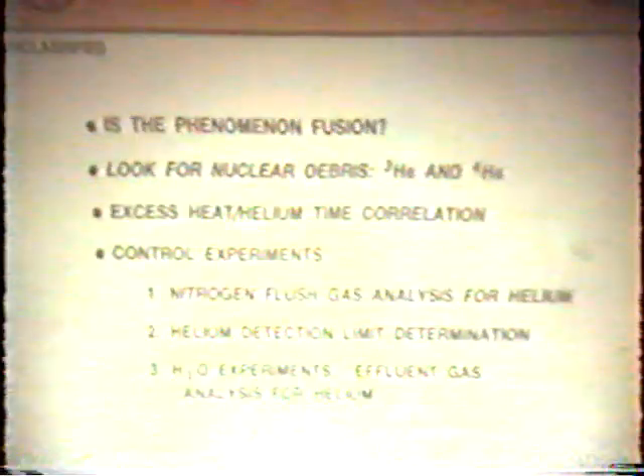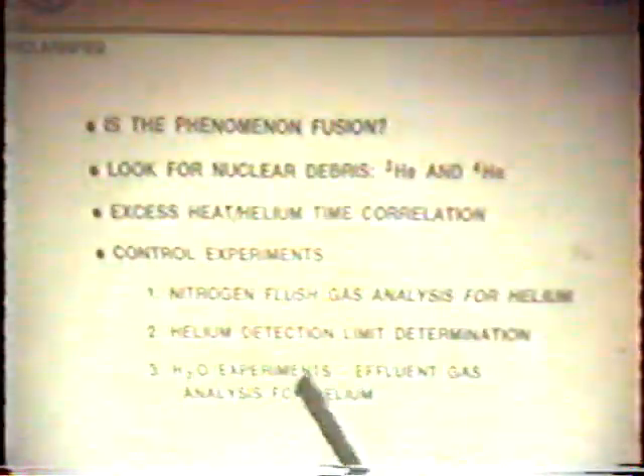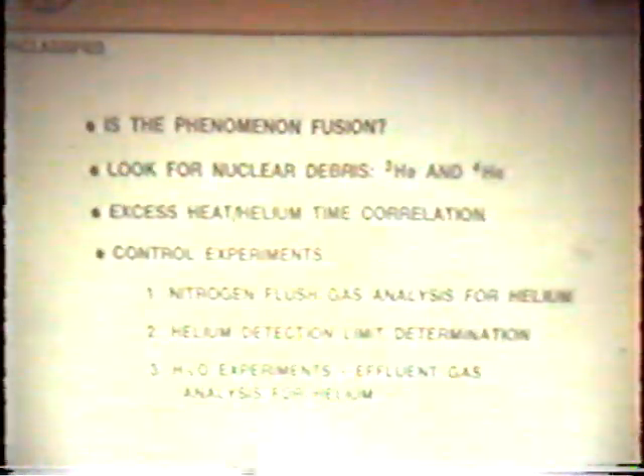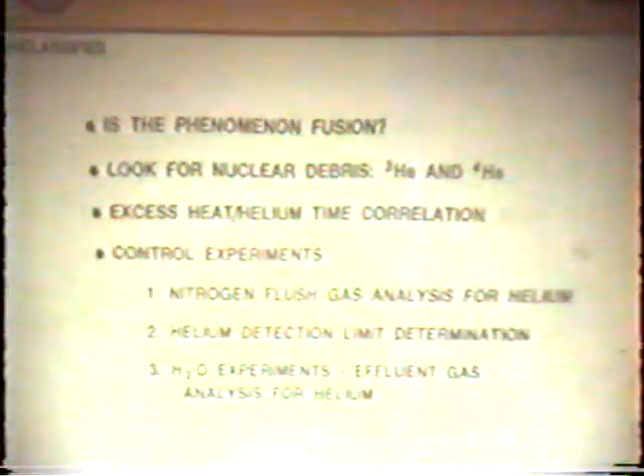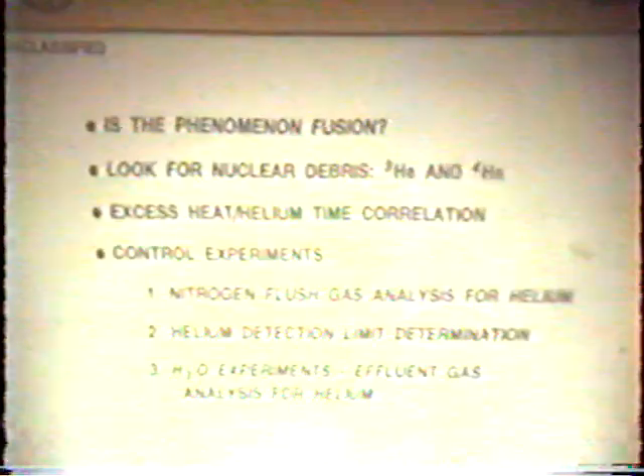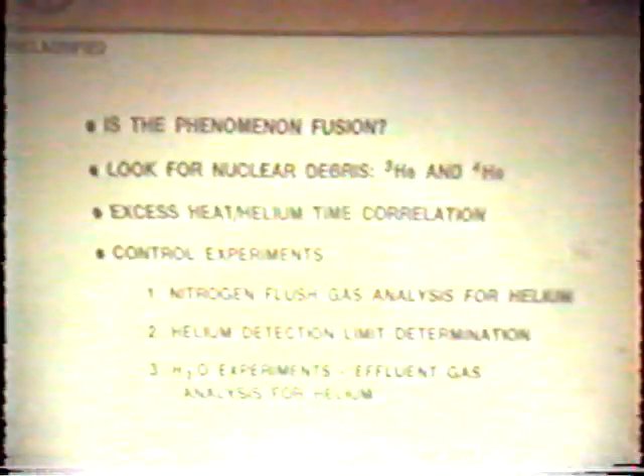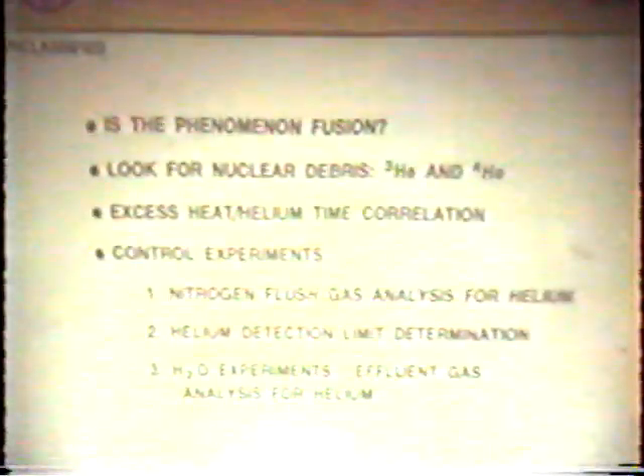You have to determine what your detection limit for helium is, and run experiments in water instead of heavy water to see whether any helium occurs there. If it's coming in from the air, you would get the helium in the light water as well as the heavy water. And this is a difficult problem to detect the helium, because you have tremendous amounts of deuterium gas coming out and oxygen gas coming out, and you're trying to look at helium in the presence of these gases coming off at a concentration of about 1 part per billion. And that's not an easy problem.